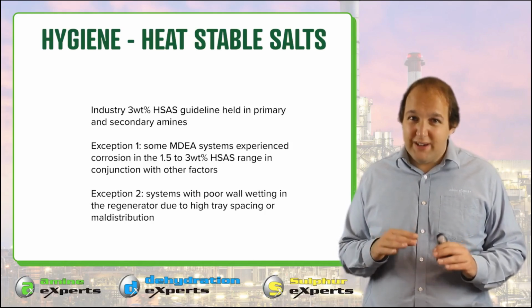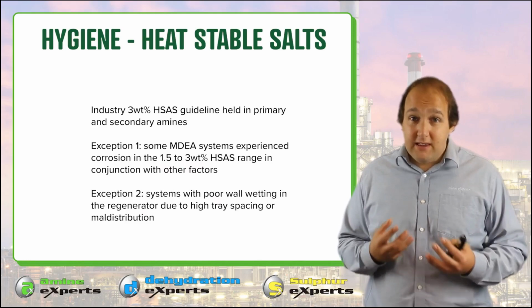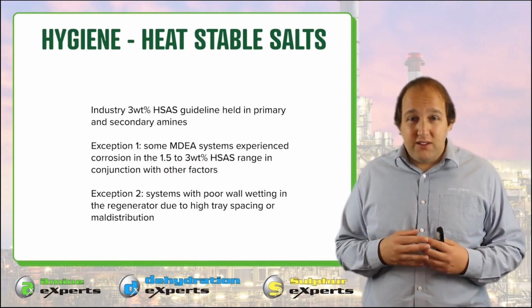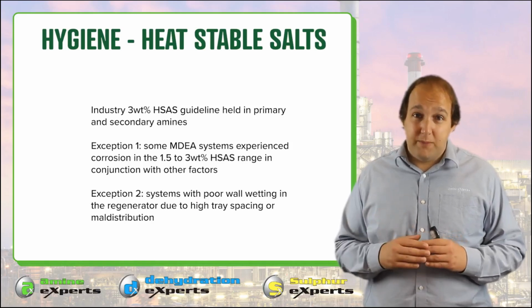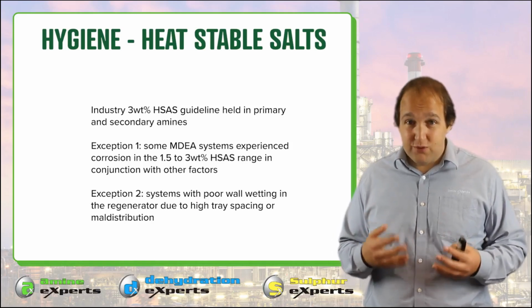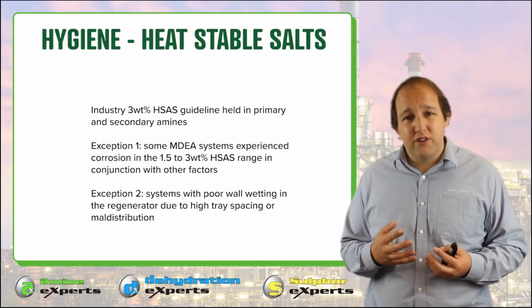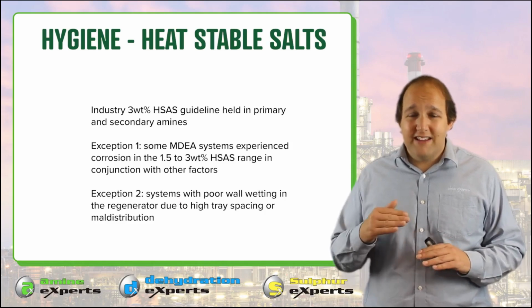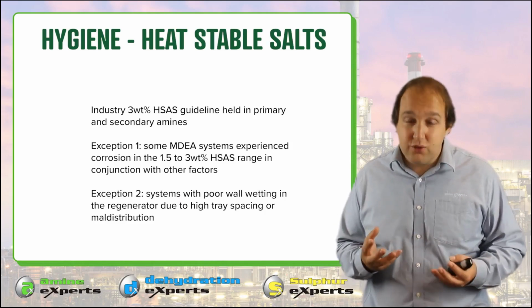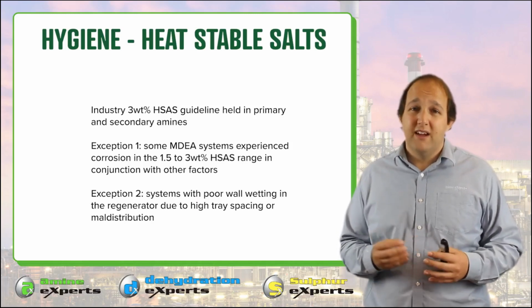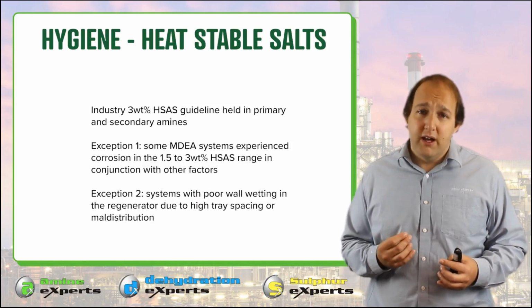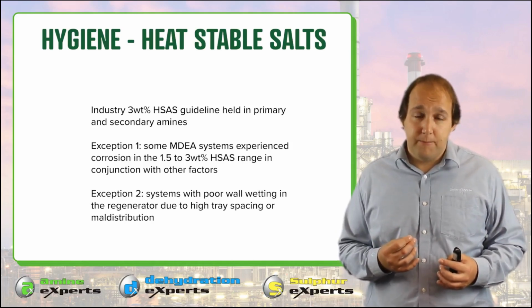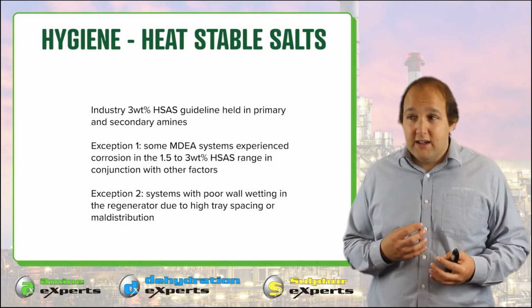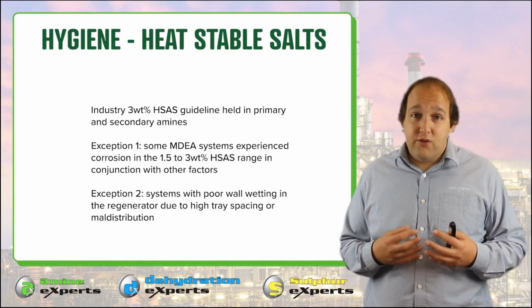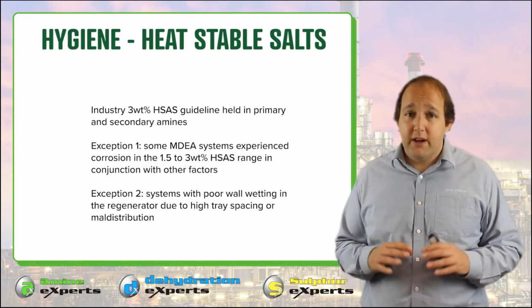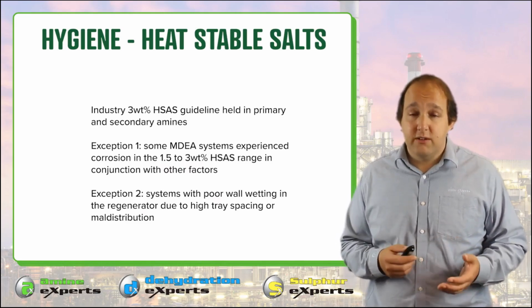The other exception we saw is when you had high tray spacing. In the industry, there's a general 600 millimeter, 2 feet space between the trays in your regenerators and absorbers. We saw corrosion in situations where there was a higher than 2 feet tray spacing. It is unusual, but you do sometimes get systems with higher tray spacings, and these systems did appear more vulnerable to attack by heat-stable salts. So if you're running MDEA or a system with high tray spacing, you may want a lower limit, say 1.5% maximum heat-stable salts.